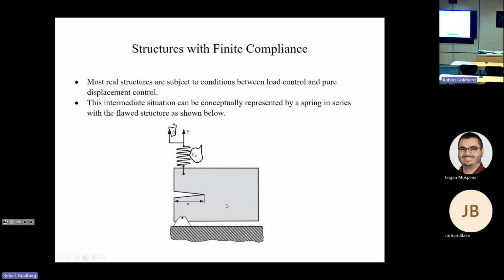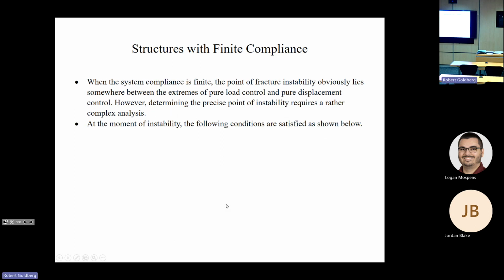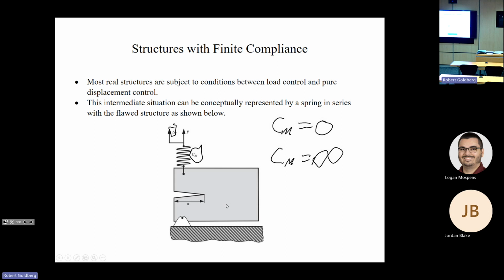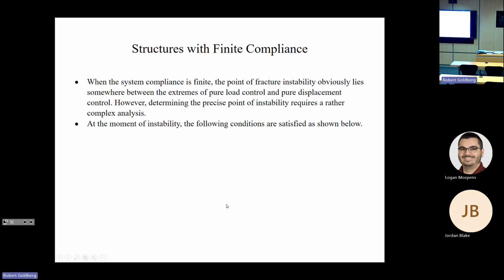So for the case of pure displacement control, the Cm would be equal to 0 because the spring would provide no resistance. The only thing we have is the applied displacement. However, for load control, if we set the Cm equal to infinity, then we just pull on it, the spring provides no resistance, and all we're doing is providing a load to the structure. So when the system compliance is finite, somewhere between 0 and infinity, the point of fracture obviously lies somewhere between the extremes of pure load control and pure displacement control.